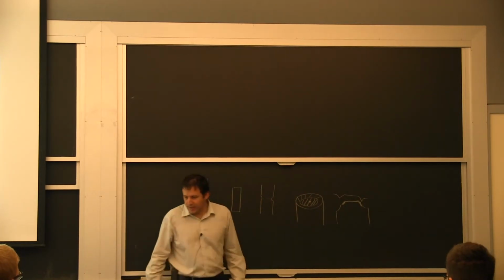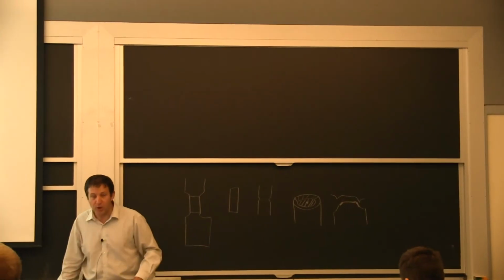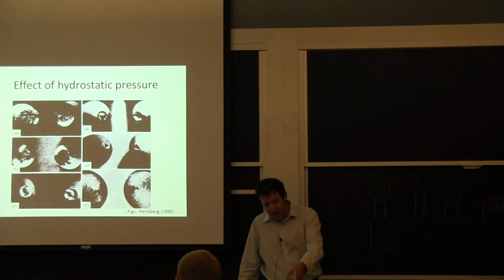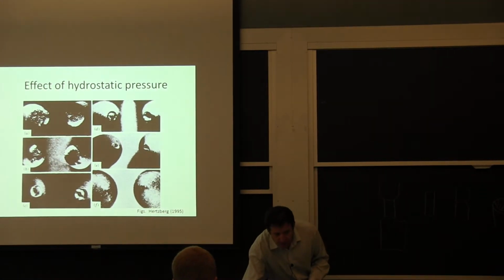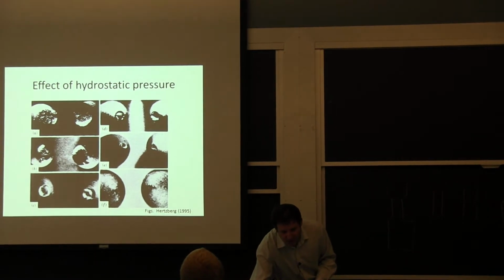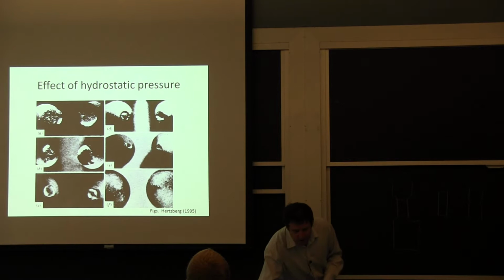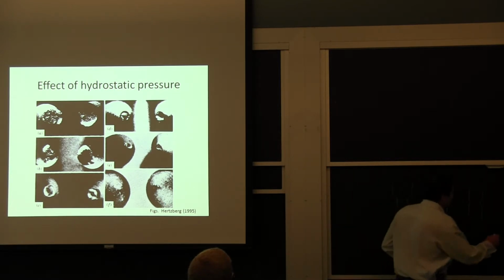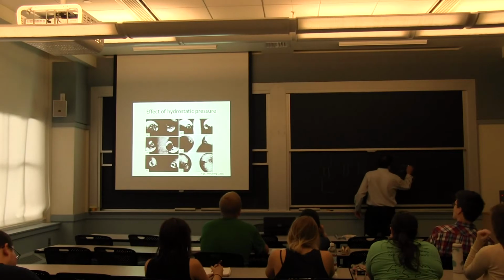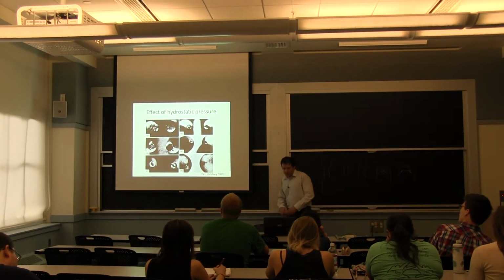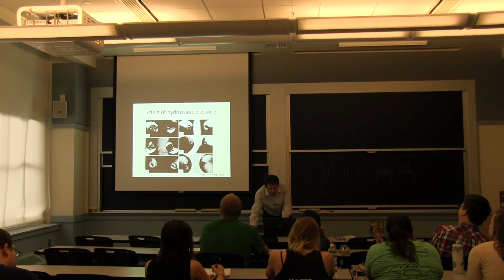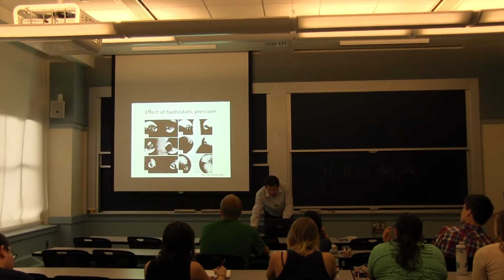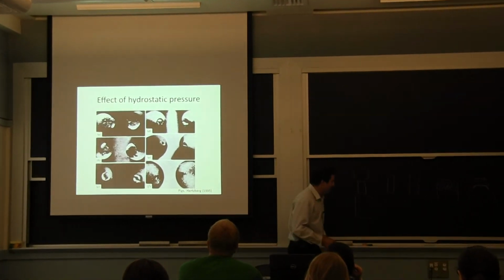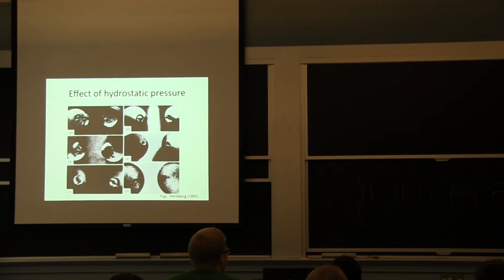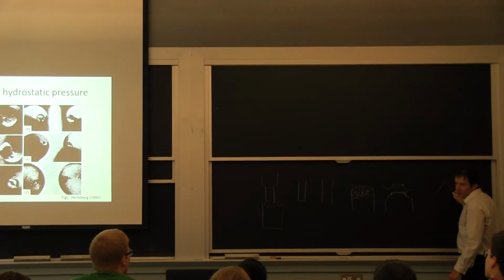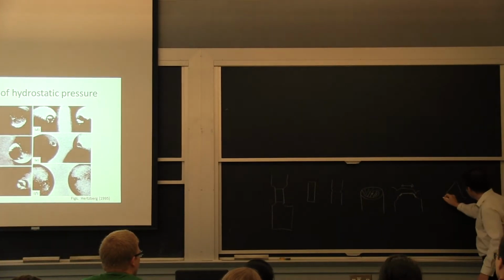The reason I mentioned that is I wanted to show you what happens when you put pressure. Now we're looking at actual sample, and you can see initially, if you do it just in the lab at atmospheric pressure, you get this zone here to be fairly big. So we're looking at this flat portion here at ambient temperature. And the flat portion, if you keep going to this image, this image, this image, this image, all the way here, there's almost none. So this sample here at the extreme is just looking as a 45 degree here with our little fillet like here.